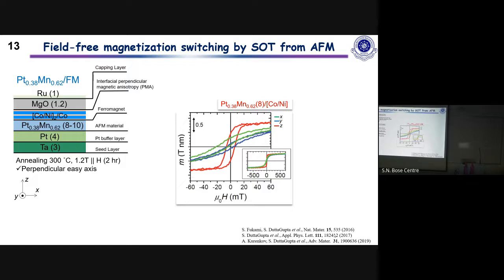When you say that it forms an alloy, then there is no sharp interface. We have never seen these different interfaces from the TEM. Usually because of the magnetization, they cannot completely alloy. Yes, but experimentally we don't have evidence for this. It's a very well known system. But from the TEM we have never seen it clearly. Probably the resolution, maybe.